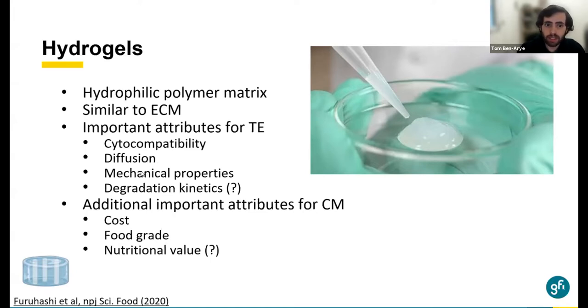We need to also assess the mechanical properties. If the gel is too stiff, then the cells will not grow in it. The hydrogel stiffness can affect the cell growth, differentiation, and cell motility, which is important in order to actually allow cells to generate tissues. Cells cannot migrate or proliferate in hydrogels which are too stiff. This also relates to the degradation kinetics. We want a hydrogel to be an initial replacement for the endomysium and allow the cells to generate their own ECM over time. So adding some kind of fibroblasts that produce ECM is also important.